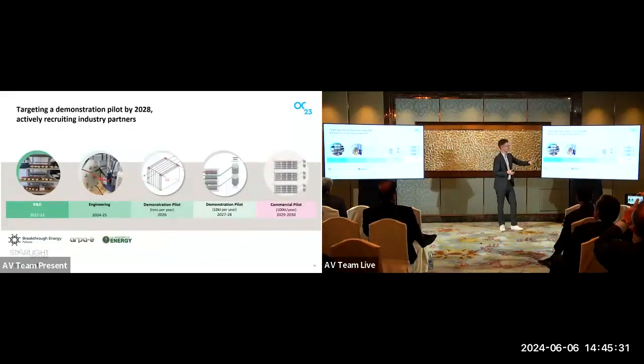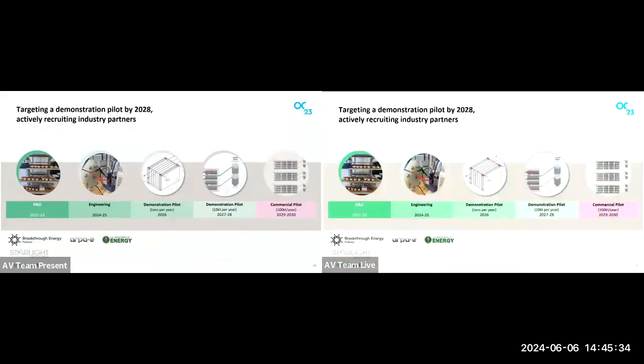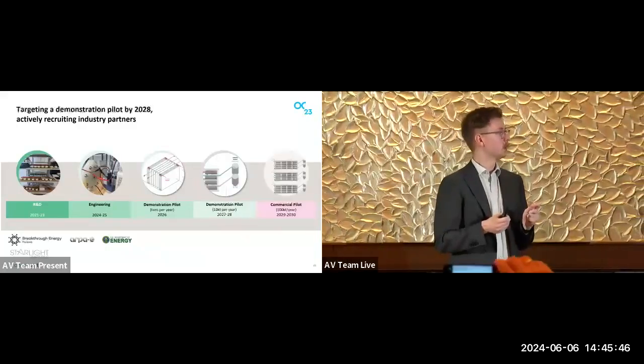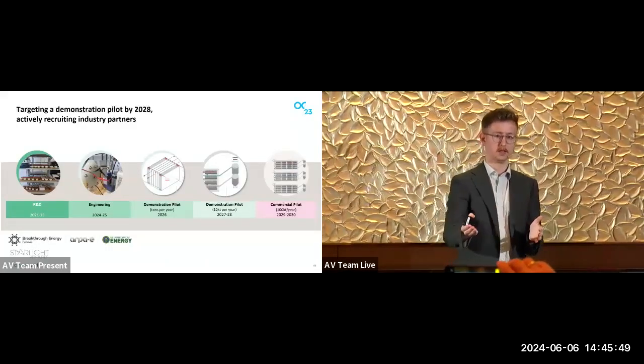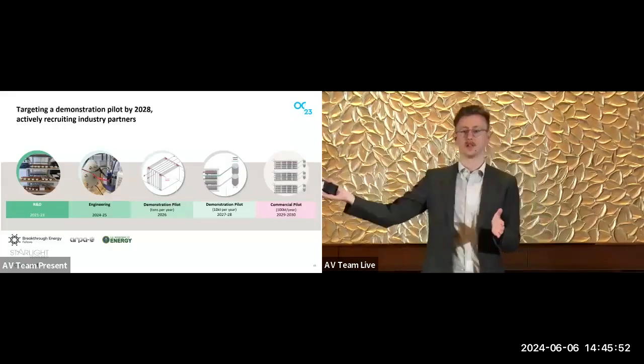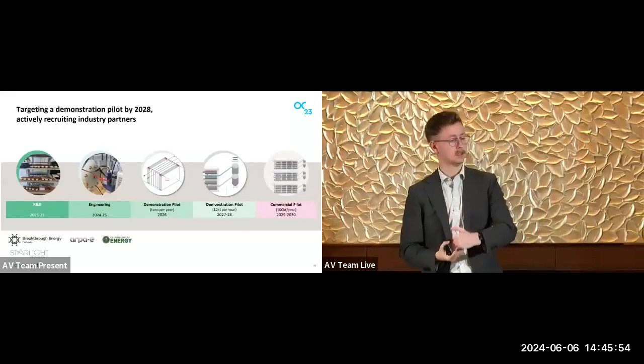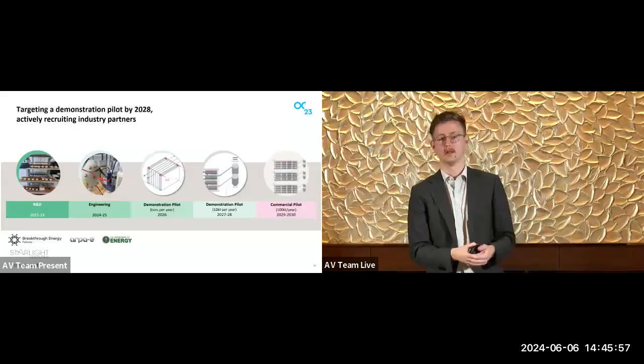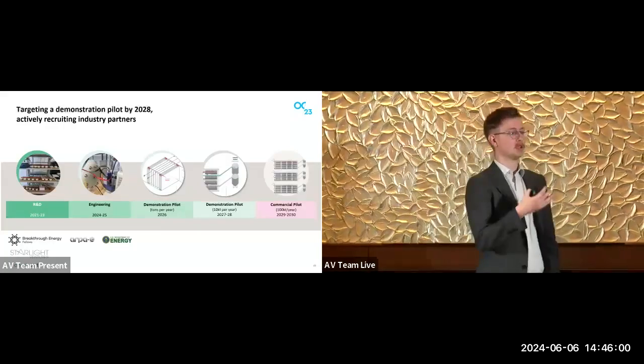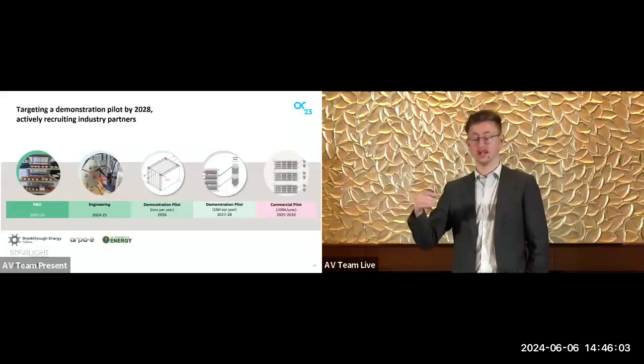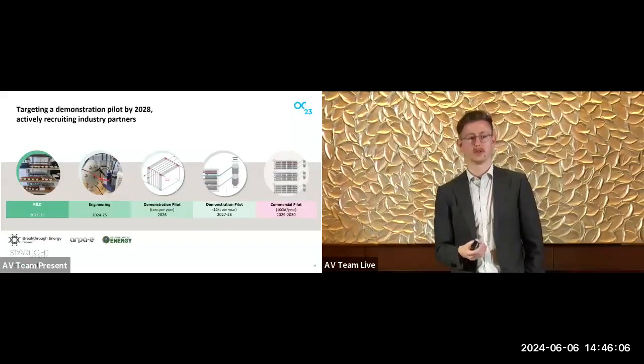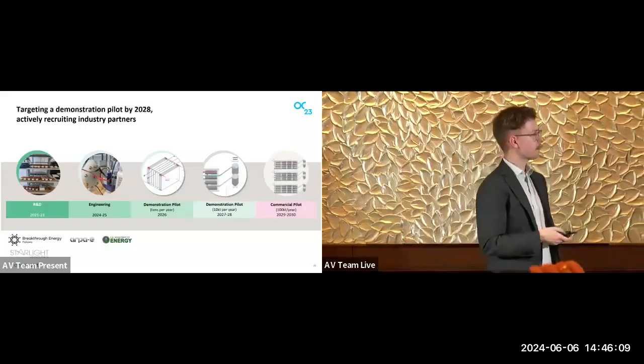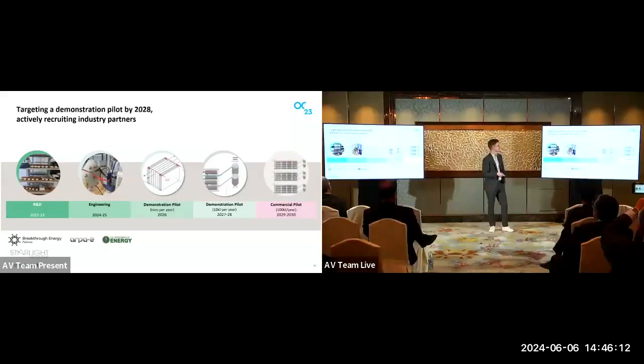We're looking to actually rapidly scale this up. So we started at the milligram scale. The first experiments we did, we made calcium silicates that were so small you can only see them in an SEM. Luckily today we're making much more material at the gram scale. And even at that scale, we're able to move the process to a continuous flow cell before even scaling it up. And once we have completed that process, we will do a demonstration in our lab, about 1 ton per year. And we're targeting by 2028 to be doing a 10 kiloton per year industrial demonstration of that technology. And of course, beyond that to a full commercial scale.